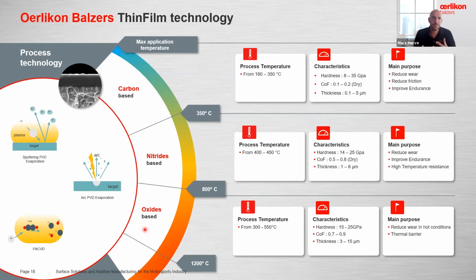So, it sounds crazy, but depending on the application, and depending on the budget of course, sometimes coating one part is going to be enough. You just have to be careful that the counterpart is not a bag of sand. You also need a highly polished surface against the coating, or obviously it's never going to work. But it's not an obligation to get both parts coated. One part coated gives you already a major benefit compared to no coating at all.